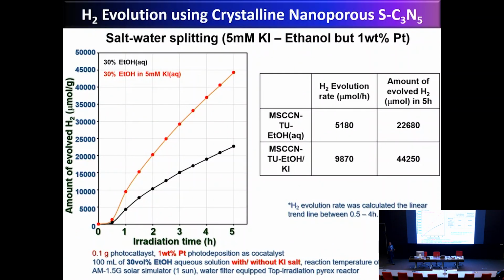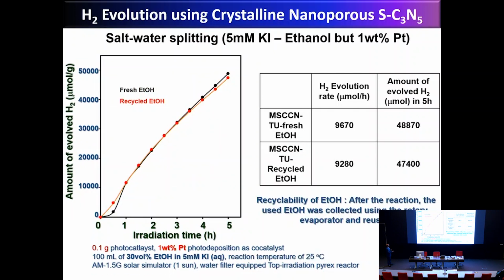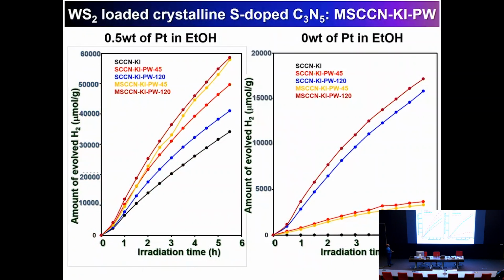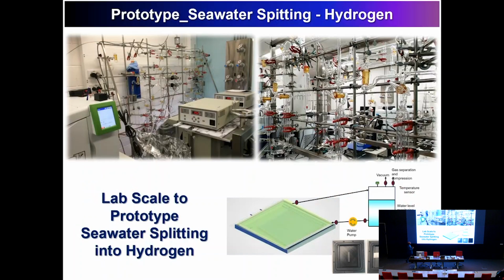Then to commercialize it, we have to make sure that we use low-cost sacrificial agents. So we use ethanol, and it gives almost similar results to the 1% platinum. We recycle the ethanol, and even after 5 hours of radiation and after 7 cycles, it works very well. Then we reduced the platinum from 3 weight percent to 1 weight percent to 0 weight percent, and it still works, but with a slight reduction in the performance of this material.